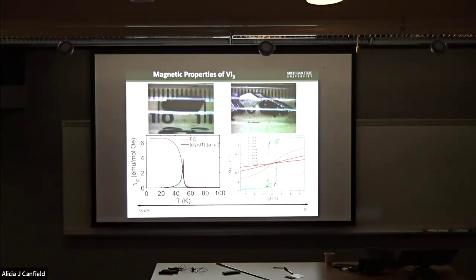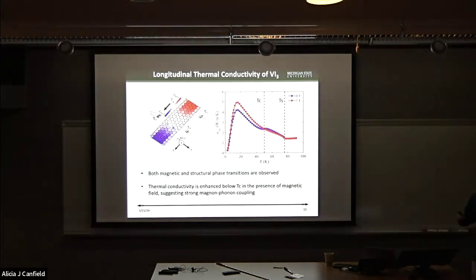So these two photos show the single crystal samples that we grow using chemical vapor transport. And we carried out the bulk magnetic susceptibility measurements. And again, we found that the system orders at about 50 Kelvin and has a large spin moment along the C direction. So everything is consistent with the literature reports. So now let's take a look at the transport data. We use the so-called one heater and three sensor technique to measure both longitudinal and transverse thermal conductivity of this system.